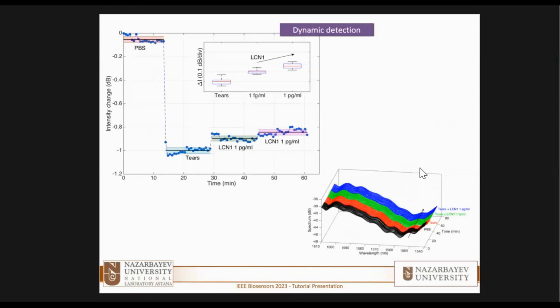If you notice, we have a quite good staircase type of response, where each concentration step is almost instantaneously assimilated by the sensor. So when we go from PBS to tears and then rise with the marker concentration, the detection is quite accurate.